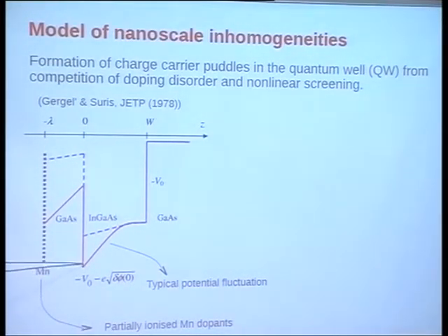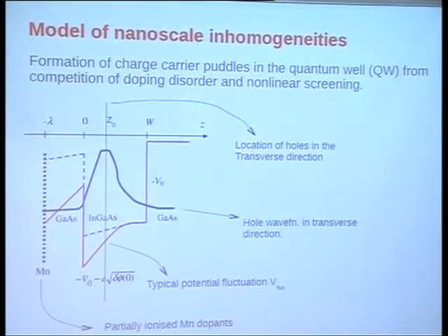On top of that, because the Mn atoms are randomly ionized, they create a random potential in the quantum well. So every now and then you have the fluctuation potential dipping below the average quantum well potential. Of course, you have the other thing oppositely also. And so the total potential should have the RMS fluctuation added to it. Whenever you get these dips, that's where the holes tend to first accumulate when you start populating it. So schematically a wave function typically will look like this. It will have some overlap with the Mn atoms here.